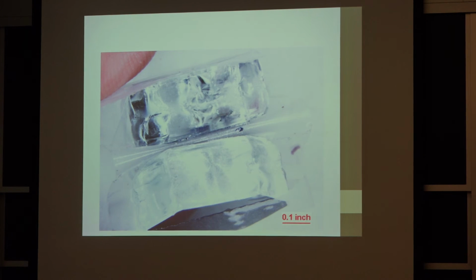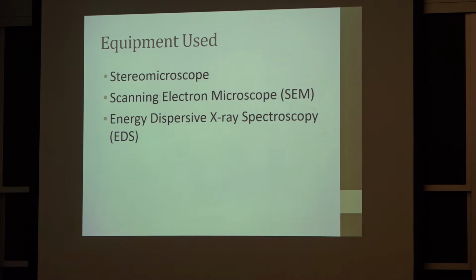So here's a piece of the glass, and when you're looking at it, actually you don't see much. Nothing really jumps out. So you have to see what techniques you can use to find the root cause. If we were going to zoom in on this area here, you see how smooth that is? Typical equipment used for this would be a stereo microscope to get some higher magnification visual, and then you can use a SEM or EDS to confirm that the inclusion is nickel sulfide. There are other types of inclusions, but EDS will tell you the approximate chemistry of the inclusion.